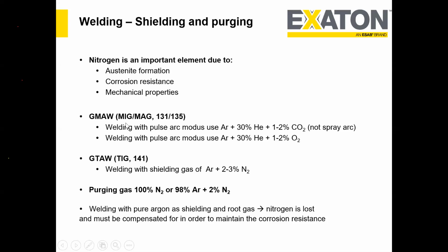So normally we recommend for the GMAW process an argon plus 30% helium or 1 to 2% CO2, or in case of TIG, we recommend argon plus 2 to 3% nitrogen as a shielding gas, and as a purging gas we can use 100% nitrogen or even 98% argon with 2% nitrogen. But be a little bit careful about 100% nitrogen, because if you use 100% nitrogen, there's a potential risk of having a very low amount of ferrite in the root.